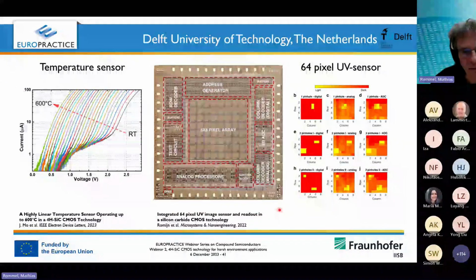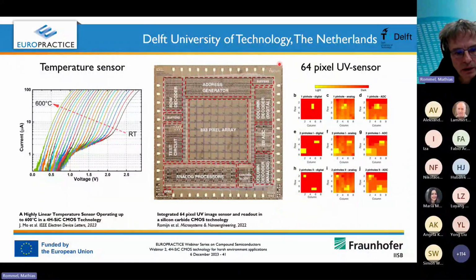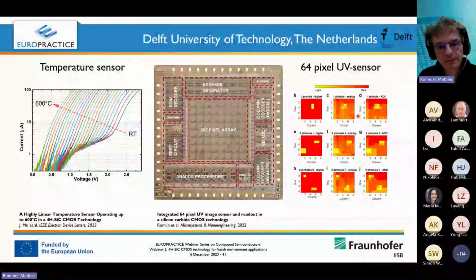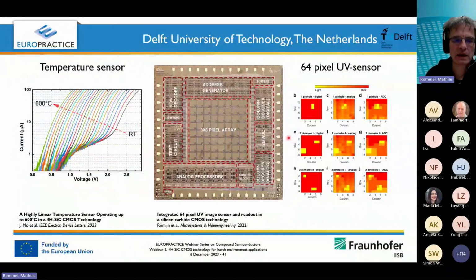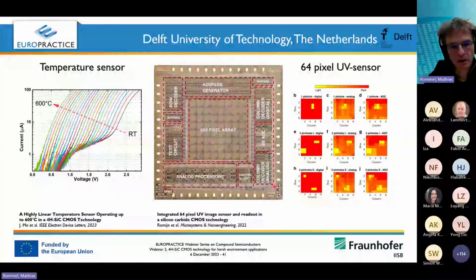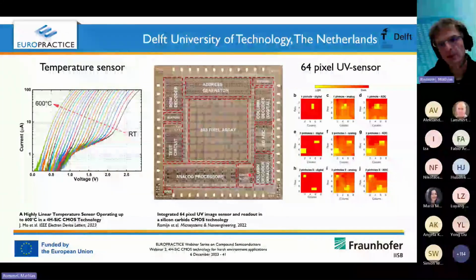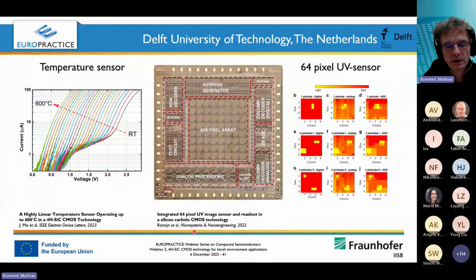In this case, this is a 10 by 10 millimeter chip with all the processing units to drive or use this 8 by 8 pixel array of UV sensors. And with this 64 pixel UV sensor, you can basically locate UV sources. That was the main idea behind it. But to achieve that, they also did all the readout and control and data processing circuits around it. And in total, it used more than 1,250 operating transistors, and they had a quite decent yield for those chips.